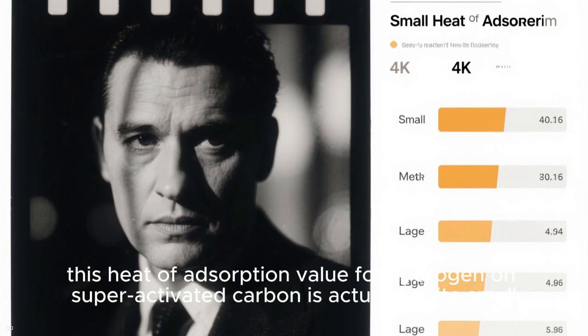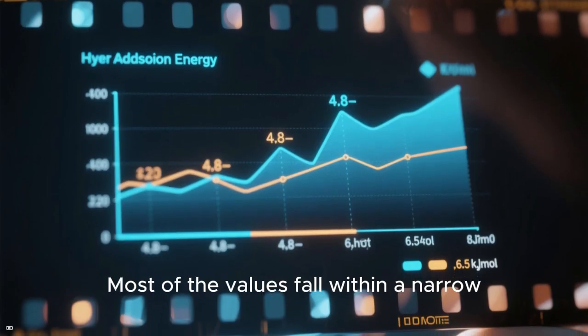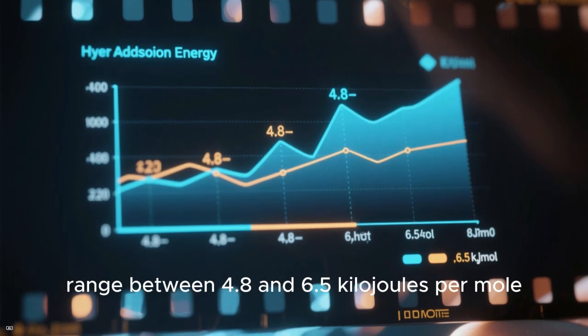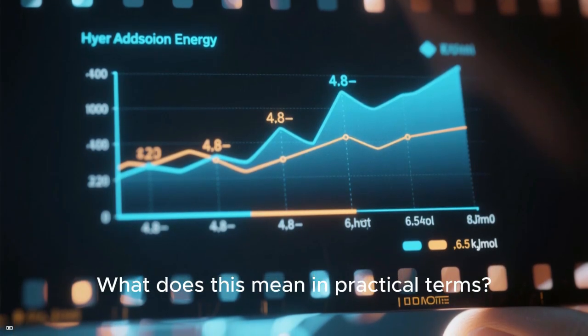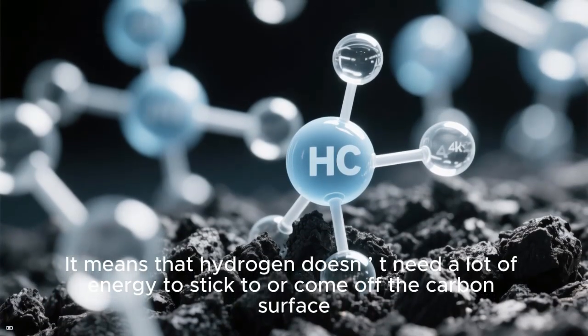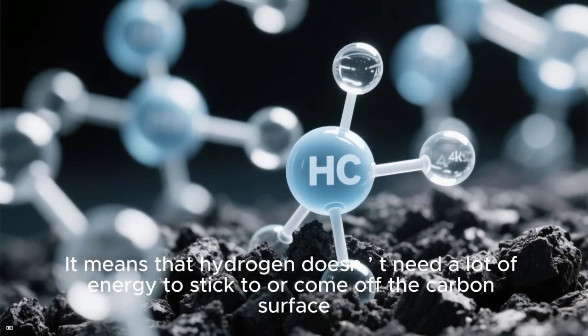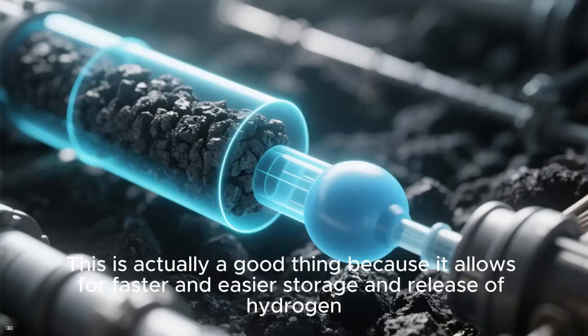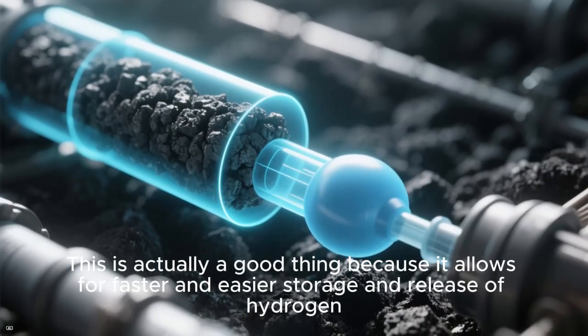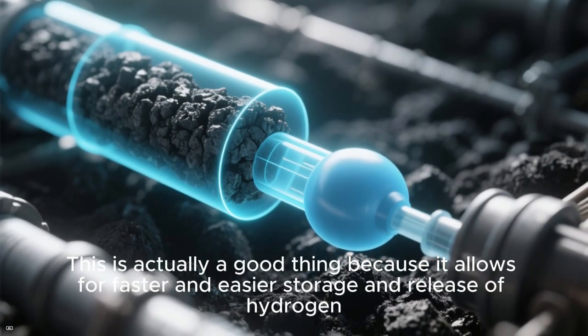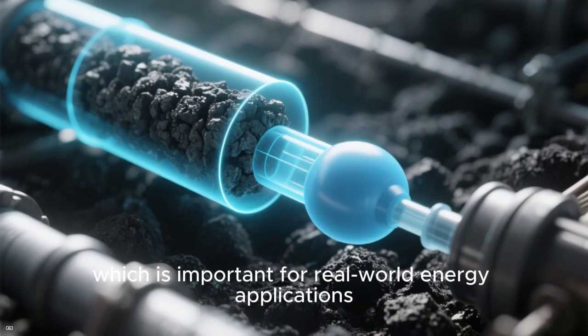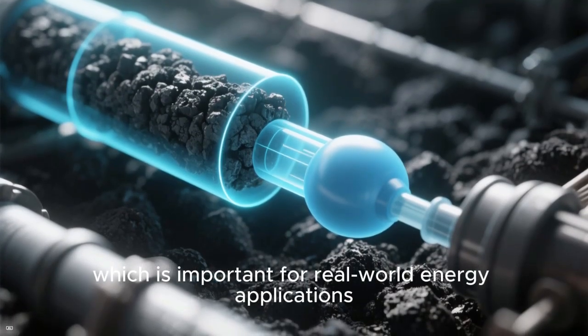From research, it was found that this heat of adsorption value for hydrogen on superactivated carbon is actually quite small. Most of the values fall within a narrow range between 4.8 and 6.5 kilojoules per mole. What does this mean in practical terms? It means that hydrogen doesn't need a lot of energy to stick to or come off the carbon surface. This is actually a good thing because it allows for faster and easier storage and release of hydrogen, which is important for real-world energy applications.